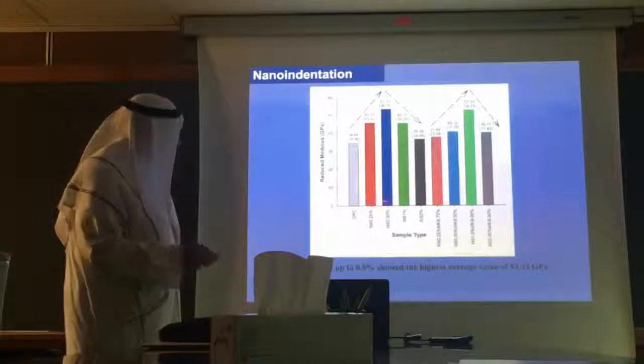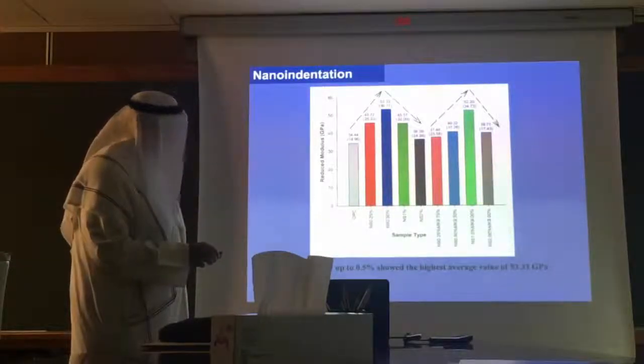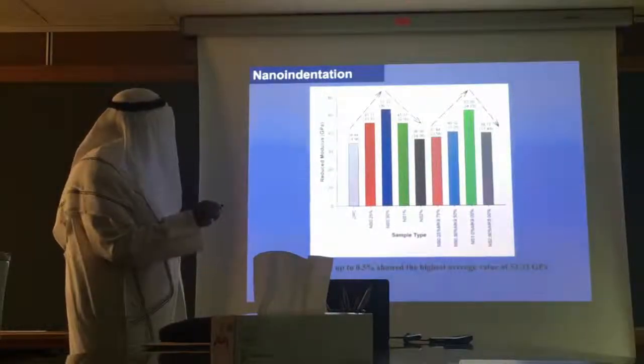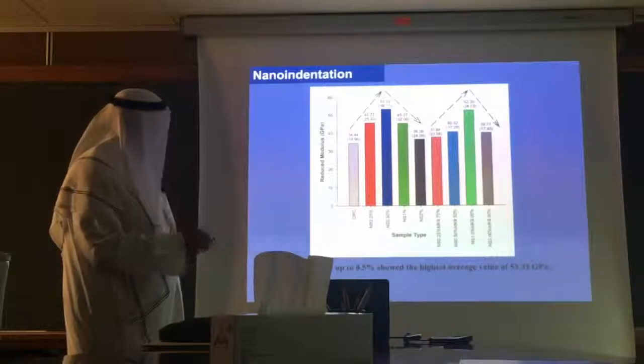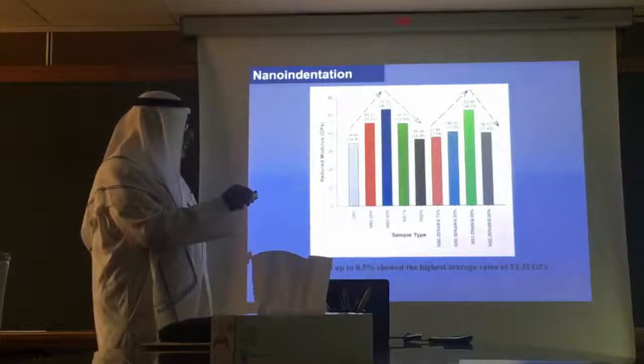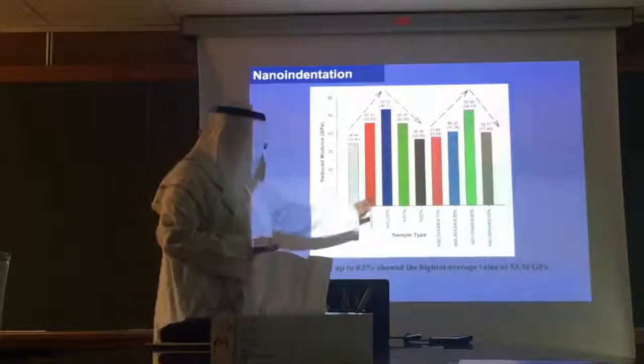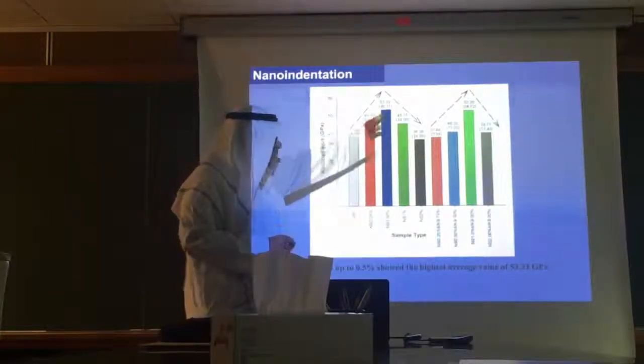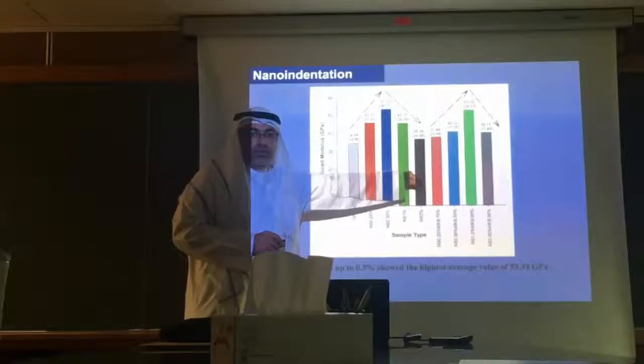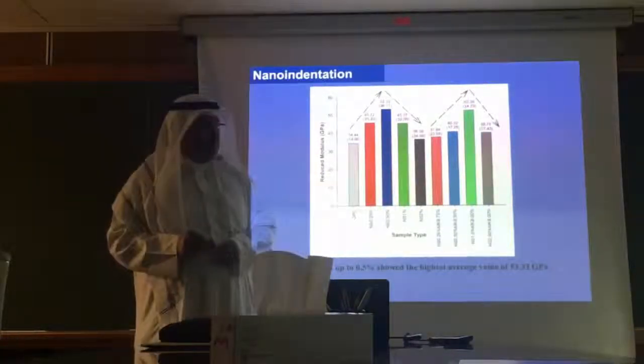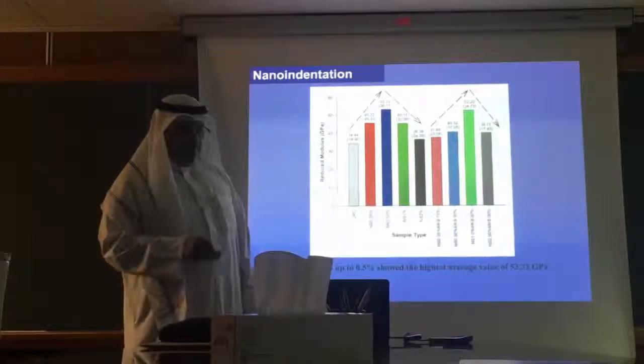And there is a physical property called reduced modulus. We found that when we add 0.5% of nanosilica, we get the reduced modulus highest. And when we add nanosilica with metakaolin, which is one type of clay, we also get a very high modulus. So there is, let's say, an optimum value for nanosilica, and if you increase it more, you are deteriorating the property of cement. The same applies for metakaolin, one type of clay that we get from China.